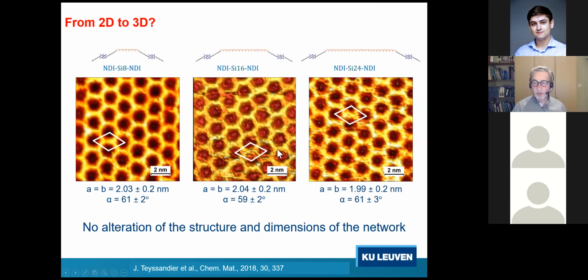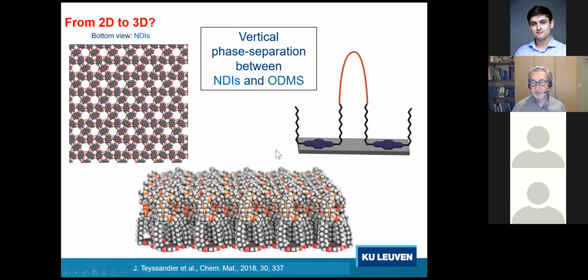Well, the only solution to this issue is assuming that the dimethyl siloxane units are actually not adsorbed on the surface, but are expelled into the liquid phase. Because the footprint of these materials on the substrate is dominated by the non-covalent interactions between these naphthalene diimide units.